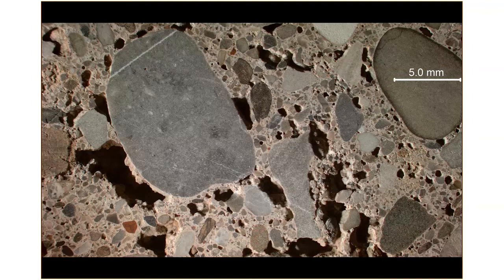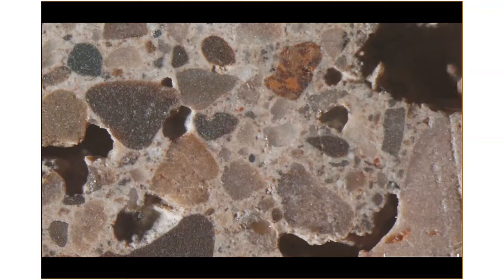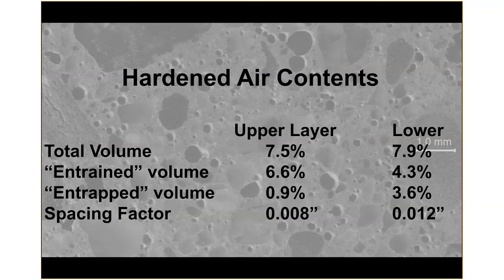Now, the paste itself in these areas is not air entrained. There's bubbles, but really all the void space is an entrapped void or under consolidation void. So we produce some hardened air void data here. In the upper layer, we found 7.5% total air, and this is right in line with any modern concrete pavement.